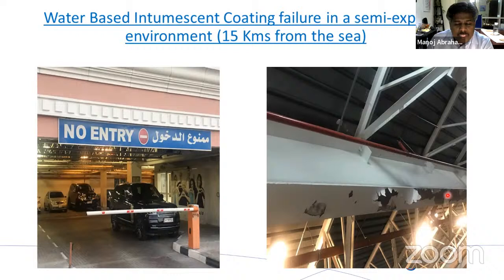And you can see that within a year's time, it started to get damaged, because water-based intumescents tend to absorb a lot of moisture. So this is not covered. Okay, so this is a ground level parking. What happened? All the humidity went in and it started to damage the coating. Even now, if you go there, you will be able to see.